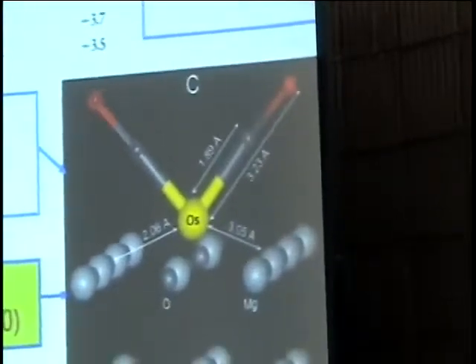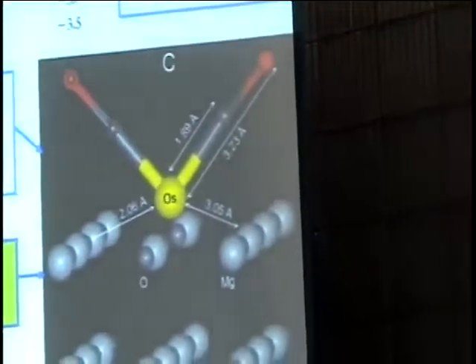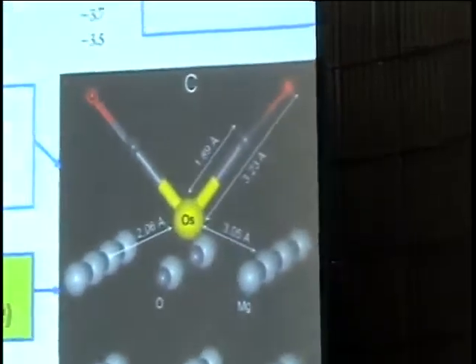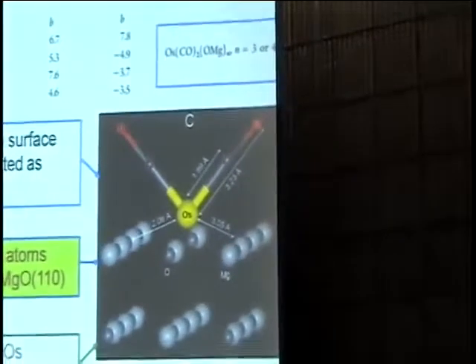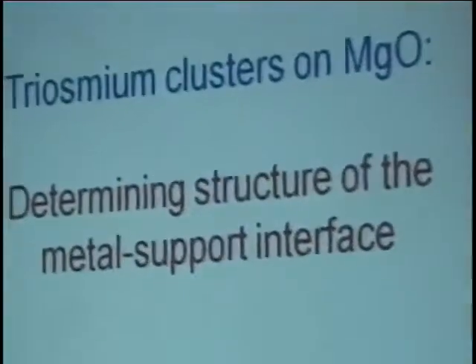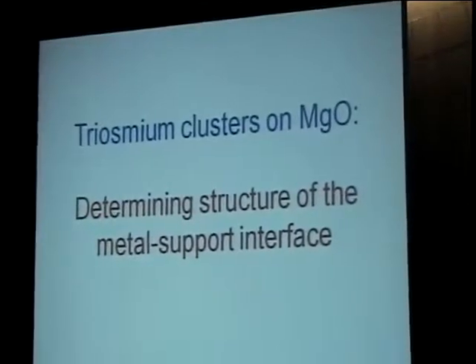And then we can put 2 carbonyl ligands in, and so we can determine a structural model, and I'm not going to show you all the details, but there it is quantitatively. And the important point about this is that if the osmium is bonded to 4 oxygens, and it's certainly bonded to approximately 4 oxygens, then the osmium-magnesium distance has to be greater than what it would be if the surface were ideal and intact. So the inference is that there's a defect site, there's a missing magnesium there to accommodate the osmium carbonyl. So there's a lot of detail coming out about the interface structure following from the microscopy with some bolstering by the spectroscopy.